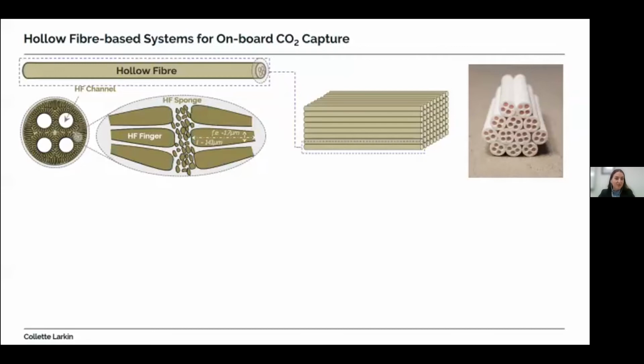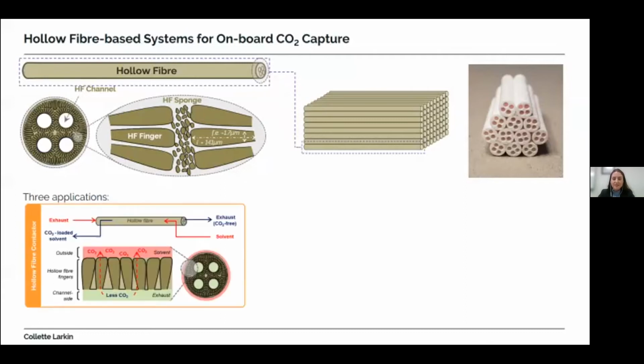And so now I will say that there are 3 applications as to how you can use the hollow fiber in order to capture CO2 in the exhaust, which I'll briefly introduce now. The first application uses the hollow fiber as a contactor. In this instance, the fingers of the hollow fiber provide a gas-liquid interface for mass transfer. Here, the material of the hollow fiber can be inert, or it can be coated to enhance the CO2 separation process. An issue that they often find is with water, causing the pores to no longer be as open and actually wetted. So they're looking into adding a material that inhibits that.